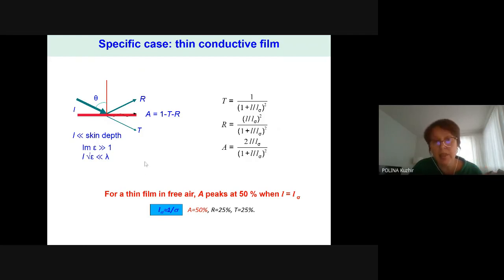Classical electromagnetics says that for a thin conductive film, whose thickness is inversely proportional to the conductivity of the film, for a particular thickness we could achieve 50% absorption of electromagnetic radiation, 25% reflection, and 25% transmittance. So remember, in order to absorb a substantial amount of electromagnetic radiation with a dielectric slab, you need at least 1/4 of the wavelength.